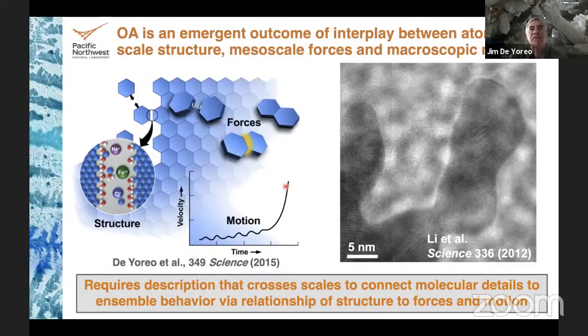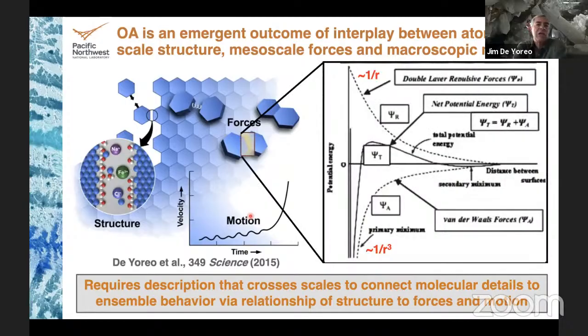Now, if we want to describe this quantitatively, like we have been able to describe crystal growth using classical theories, we need a description that crosses scales to connect these molecular details of structure to the ensemble behavior via this relationship of structure to forces to motion. Now, the way that this has traditionally been viewed is in the sort of simplistic DLVO theory, where there are two dominant forces. One is a repulsive electrostatic force, which goes like 1 over R, and the other is a strongly attractive van der Waals term, which takes over at very short distance because it goes like 1 over R cubed. And the result of that is a secondary minimum, and then a barrier, and then the contact. And the ability for particles to be captured in the secondary minimum and orient themselves before overcoming this barrier is the hypothesized view of how you end up with oriented attachment.